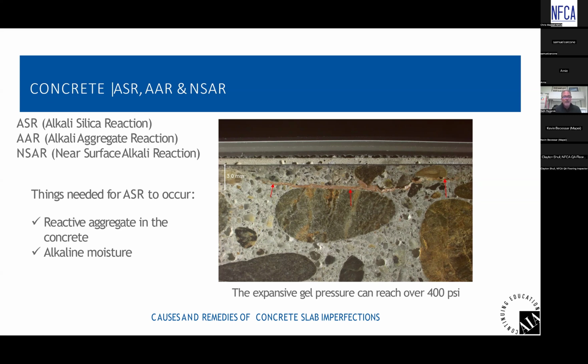And something that is not very common in concrete for this to happen is a reactive aggregate. So there are aggregates that are specified for concrete, ASTM standards. These aggregates have to meet the aggregate standards for concrete, and aggregates are tested for reactivity, and they are not permitted to be used in concrete. You know, we're a manufacturer of patching and leveling materials. We test all of our aggregate by third party to ensure that the sand and aggregates that we're purchasing are not reactive aggregates. But unfortunately, reactive aggregates sometimes slip in.